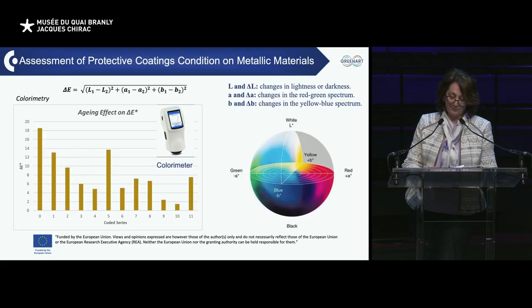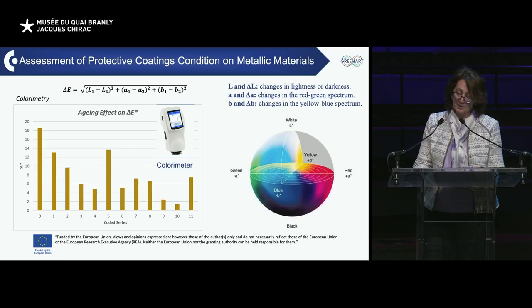When we analyze color changes and quantify color alterations or possible aging impacts on the samples, there are a lot of things to consider. However, for a quick and practical overview, we often use the delta E calculation. It's essentially a measure of the overall color difference, and you can see the formula up here on the slide. Delta E takes into account 3 key parameters: the difference in lightness or darkness, represented by L and delta L, the difference in red and green, shown as a and delta a, and the differences in yellow and blue, indicated by b and delta b. Simply put, a larger delta E value signifies a more significant color change. And if the change is substantial enough, we can then see it with the naked eye.